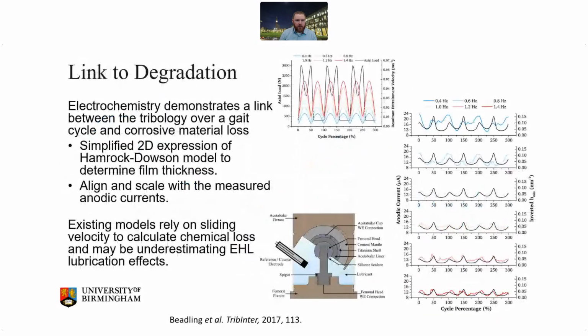And one of the things that I did during my PhD was try and link that corrosive degradation at the bearing surface to the lubrication of the device. So I did some fairly simple tests where I just varied the speed, the frequency of sliding, in order to change the entrainment and the generated lubricating film, and found a fairly close correlation between the anodic current that I was measuring from the bearing and that predicted film thickness. What was interesting around this is a lot of the existing tribocorrosion models at the time would predict that as your sliding speed trended to zero, your corrosive degradation would also trend to zero, because if you're not sliding, you're not depassivating.